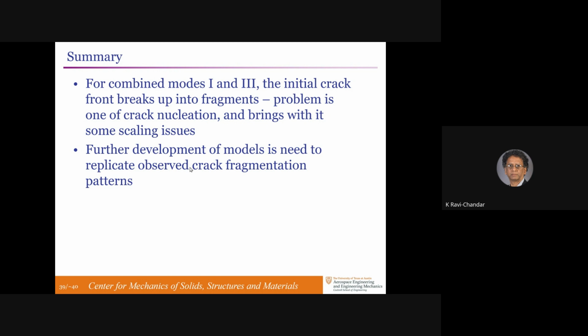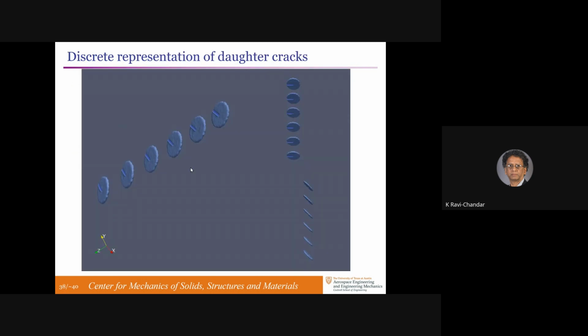I was curious about the plot that you showed, where you use linear stability analysis. You need a certain amount of K3. Right. But experimentally, even if you have very low K3, it still happens. But the skew character is a function of K3, right? So that means if your K3 is very small, the kinking should also be very small. Right, it is. But it's visible. Like if your K3 is really low, it should just go almost like...